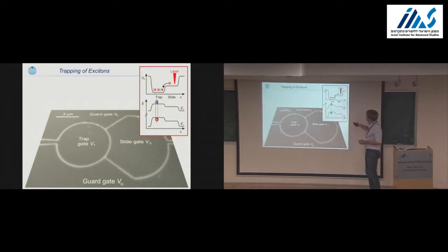When you talk about these indirect excitons in terms of Bloch waves, the conduction band for the electrons has a minimum, and for the holes it's a maximum. And here now, in this simplistic sketch, this is the so-called binding energy, which in gallium arsenide is roughly 3 to 4 meV, depending a little bit also on the quantum well width.